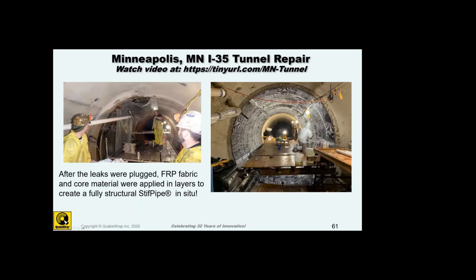But another way that this system, StifPipe, can be used is if you have a project where it is difficult to slip line it with a pipe, we can take the materials inside of the pipe or tunnel and line it, and layer by layer apply it the same way as that StifPipe, like build a StifPipe by using your host tunnel or pipe as the mold for our material. And that's what we were doing in this project in downtown Minneapolis, where this tunnel is about 150 feet below grade. So we took the material down a shaft, and then they traveled to this damaged area, which was very severely corroded and weakened. And we built a fully structural liner layer by layer, inside of that pipe.